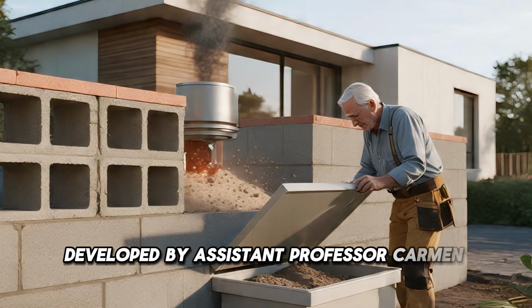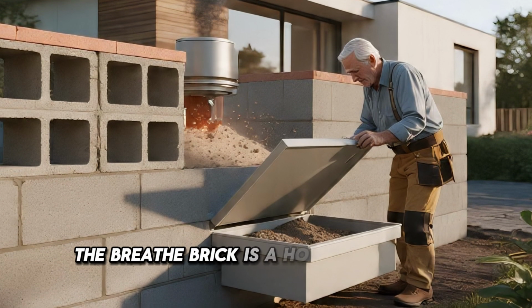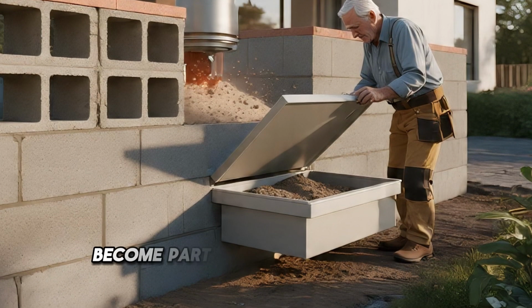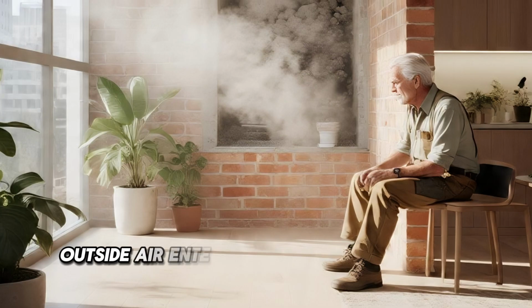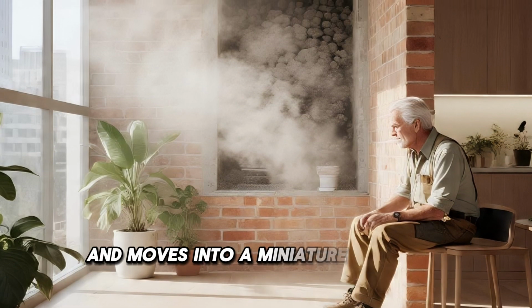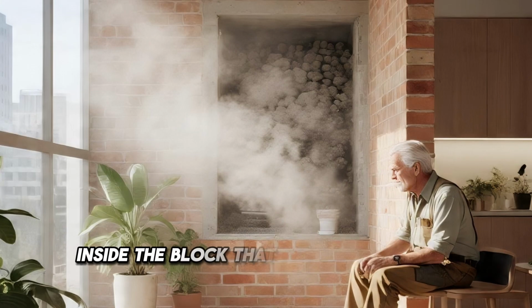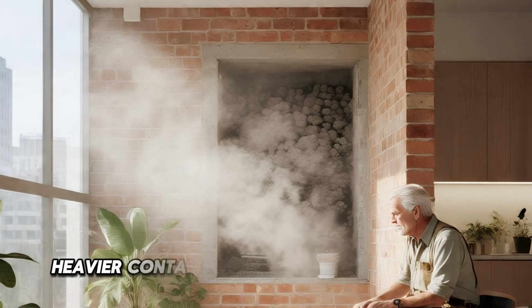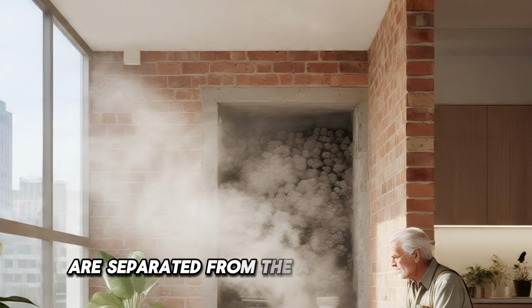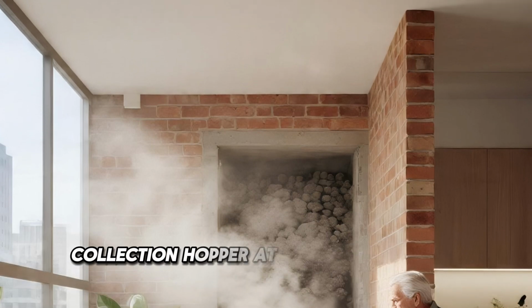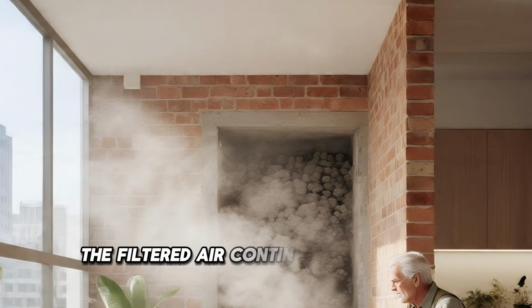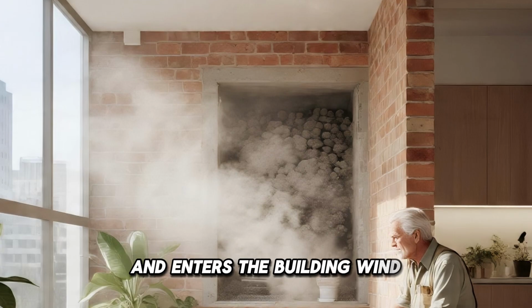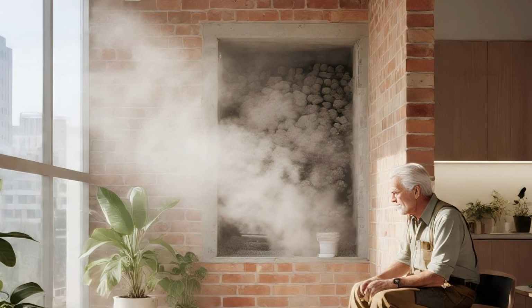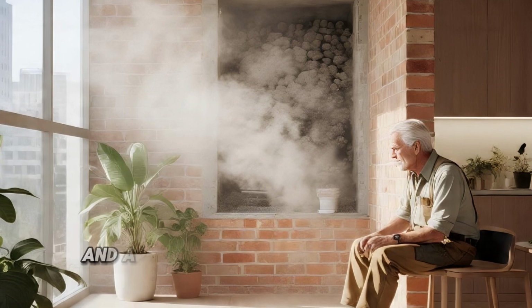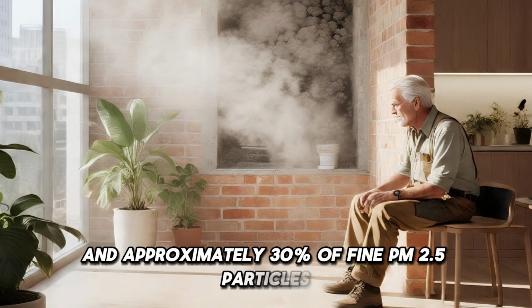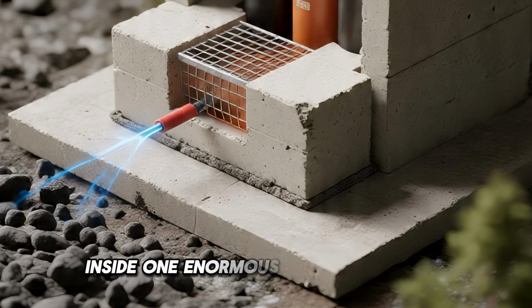Developed by Assistant Professor Carmen Trudell at Cal Poly, the Breathe Brick is a hollow concrete masonry block designed to become part of a building's normal ventilation system. Outside air enters through the face of the brick and moves into a miniature cyclonic filtration chamber inside the block. That cyclone spins the incoming air. Heavier contaminants such as dust and soot are separated from the airflow and fall into a removable collection hopper at the bottom of the wall. Meanwhile, the filtered air continues through the system and enters the building. Wind tunnel testing showed that this passive masonry system could remove 100% of coarse particles and approximately 30% of fine PM2.5 particles. It is almost like living inside one enormous passive air filter.